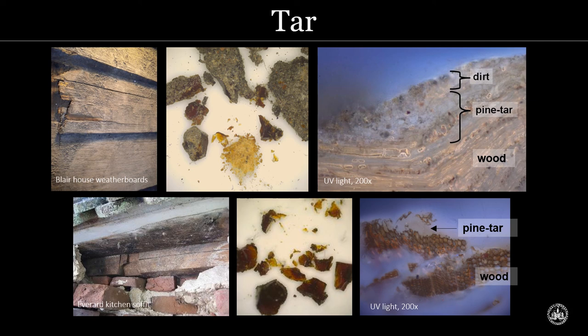And I put a few bits on a glass slide, slowly heated it, and I knew it was tar right away because you had that immediate odor of tar, very distinctive. I also identified it with FTIR. But now in the cross section, it would have been so easy to miss if you didn't know it was there. So these images, top and bottom, I'm showing in ultraviolet light, because in the visible light image, you really can't see anything at all. So we have the wood here and here, and here is the pine tar and a lot of that embedded dirt on the surface. So very, very difficult to distinguish. And this has taught me to always look out for tar on buildings, because it could be very easily missed.